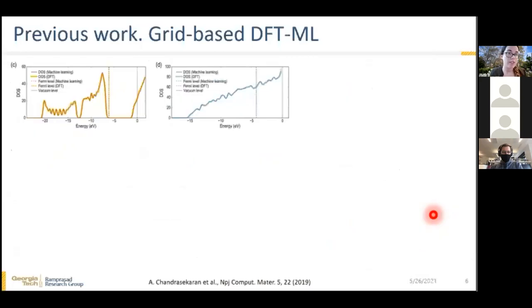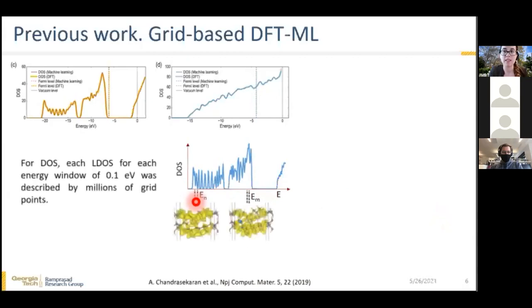Now, if using a grid-based approach for the density is already expensive, it is so much more for the case of the density of states. If we look at the charge density as the spatial distribution of the electrons, the density of states can be seen as the energy distribution of the electrons, or charge density. Now, to describe it in terms of the grid points, we first have to separate the density of states into energy bins, which in this work were of 0.1 eV. And then within each energy bin, we need to obtain the partial charge density, which is the distribution of the charge density within that energy range.